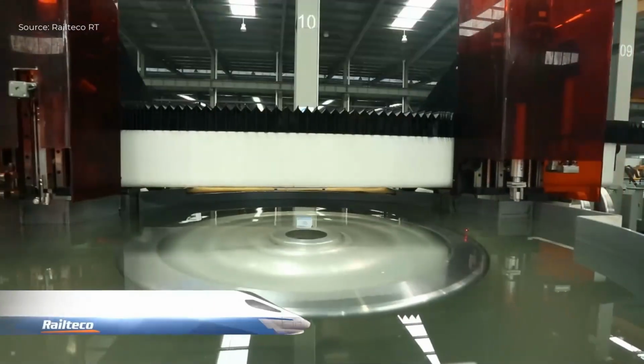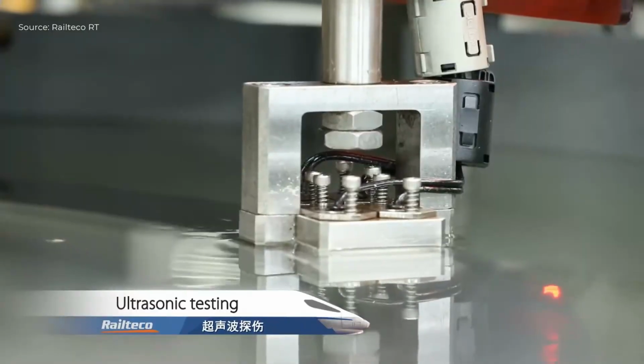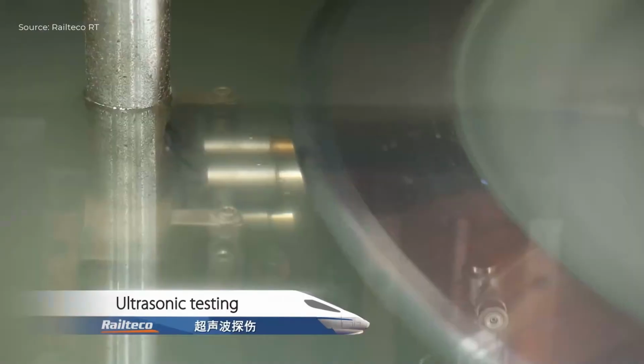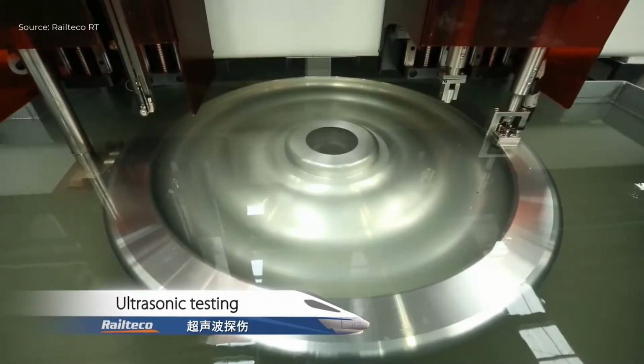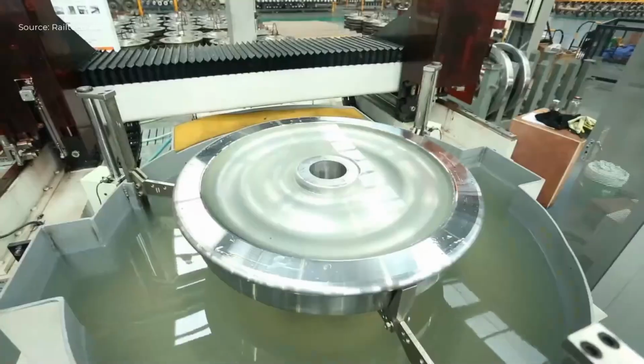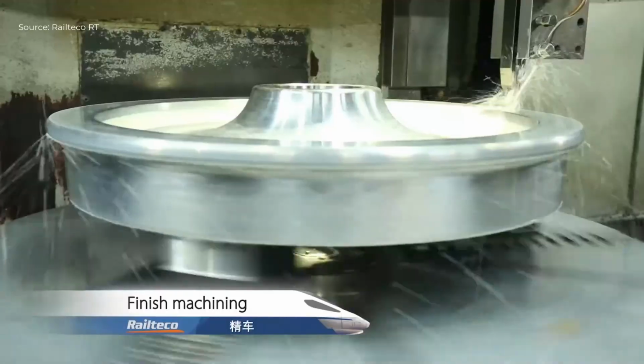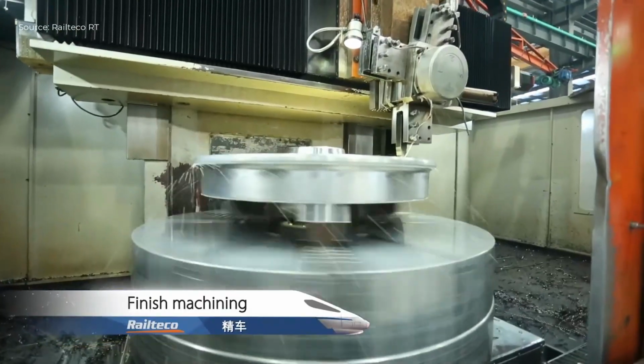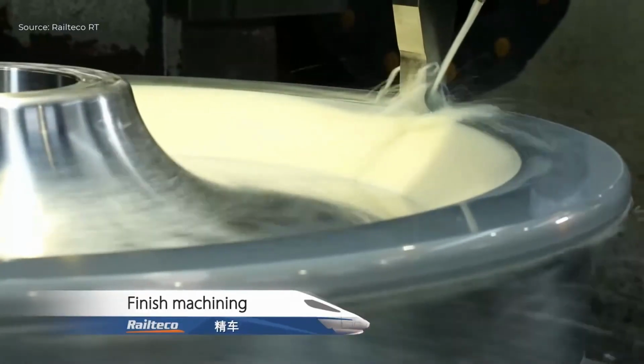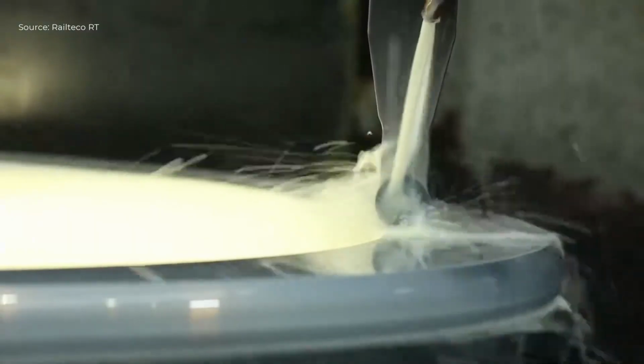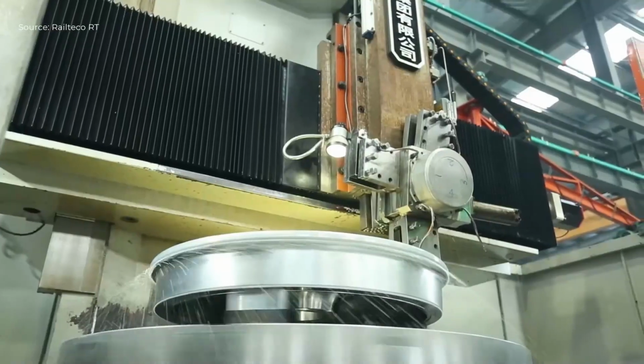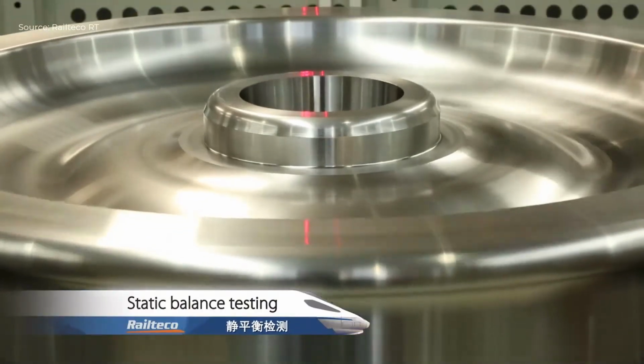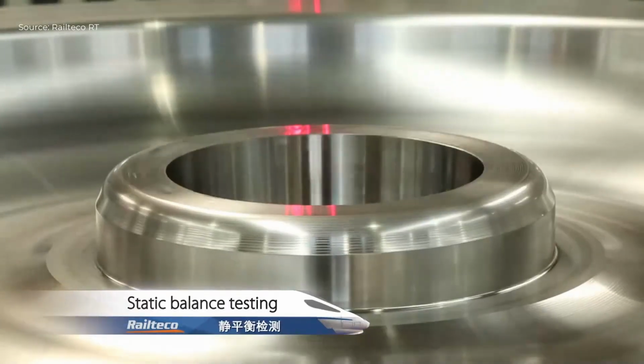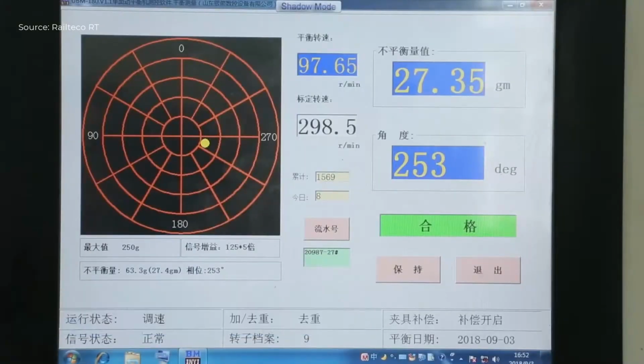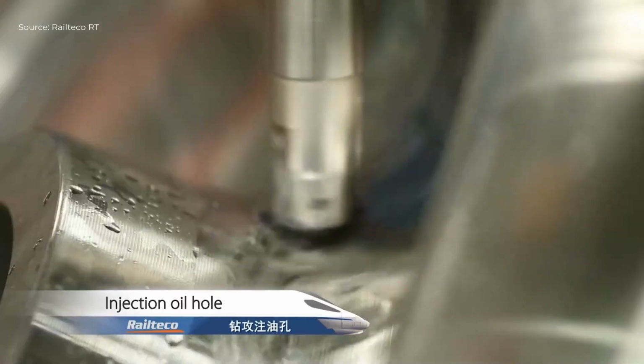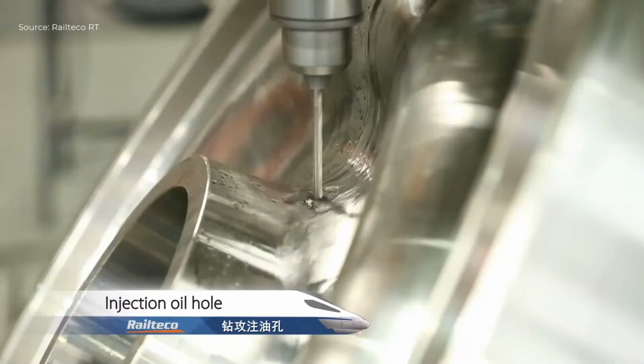Surface hardness is measured using an automatic Brinell or Rockwell hardness tester. Static balancing is performed with a vertical centrifugal single-plane balancer to ensure stability during rotation. Accepted wheels are automatically marked for traceability. Fluorescent magnetic particle inspection is used to identify surface cracks. For special applications, oil hole drilling, web plate hole machining, and internal bore grinding are executed using dedicated equipment. All data is recorded in the system for quality control before the wheels are cleaned, packed, and dispatched.